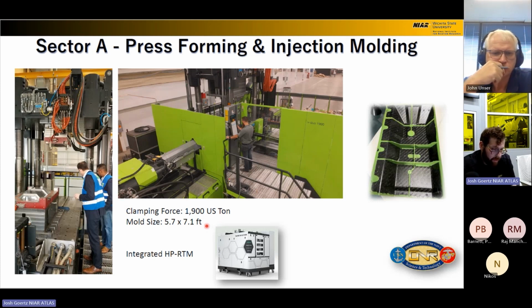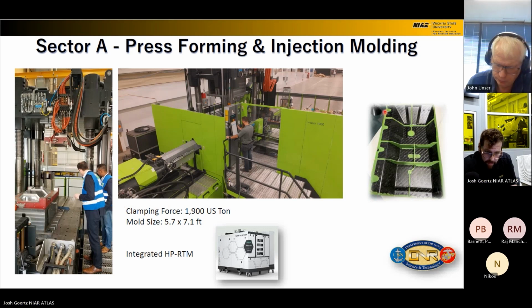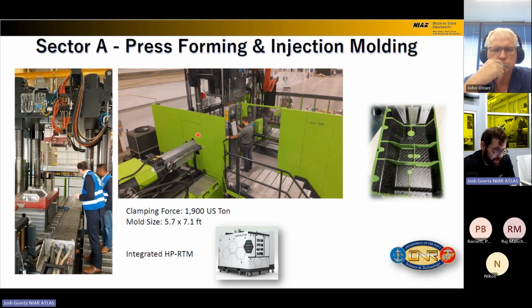And we've been retrofitting this machine to run with the higher temperature PEEK-based thermoplastic materials for doing stamp forming and consolidation of panels. And then the same machine, in addition to the stamp forming capabilities, also has high temperature injection molding, which is this unit off to the left of the machine, which is a screw extruder and then a hydraulic ram for injecting through a hot runner system, so that you can reach all the different parts of your mold component.